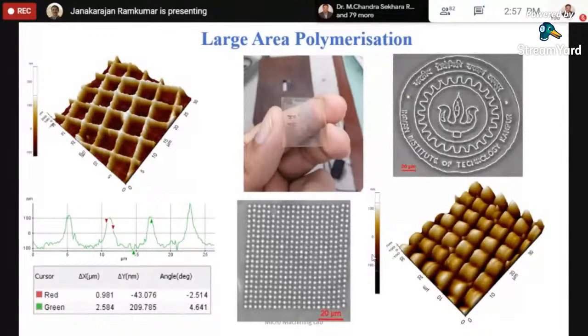This will be used as a die, like a stamp. We use this as a stamp, pour polymer, and try to replicate the image on the polymer, and then we do annealing or something. There is a uniform shrinkage happening, and we will try to get nano textures or nano features. So these are the things which we develop through our machine. These are the spots which we have developed on top of a polymer sheet for various applications.